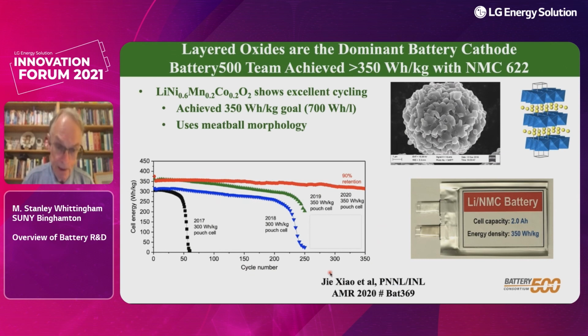This is data collected by the Pacific Northwest National Lab group of Jie Xiao. And she makes these cells and sends them to Idaho National Lab to be tested, so it's independent. And these are on 60% nickel. And you can see how things have changed over the last 3 years. In the first year, we got just 50 cycles out of this at 300 watt-hours per kilogram. A year later, we're up to about 225.